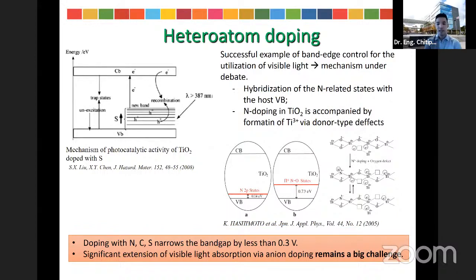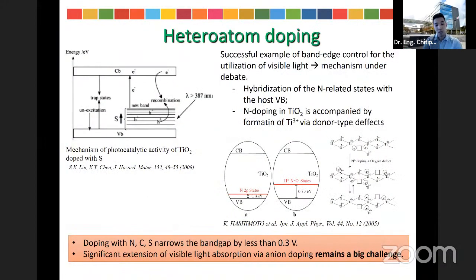Also, for further enhancing the photocatalytic activity, doping the semiconductor with 2 kinds of atoms, which we call co-doping, has gained considerable attention due to its higher photocatalytic activity compared with single element doping. For example, in this slide, I show you the preparation of sulfur or nitrogen doped TiO2. After doping with sulfur or nitrogen, it generates a new trap state above the valence band top, as you can see here in the red line. The generation of the new trap state can reduce the energy band gap, resulting in enhanced visible light ability, and also decrease or avoid the recombination of the electron-hole pair.